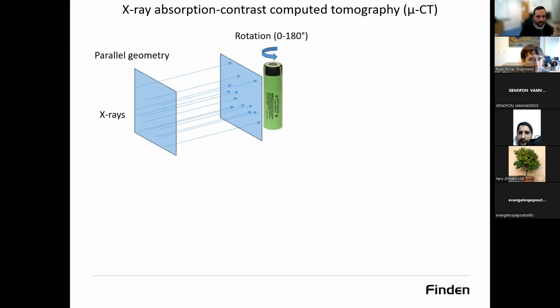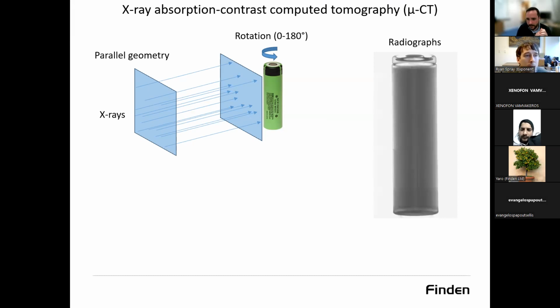But before we go there, let's take a step back and talk a little bit about absorption contrast tomography. You are probably familiar with these techniques through hospitals, so medical X-ray CT. It's essentially the same technique that we use to study materials and devices. In the simplest implementation, you have here a parallel beam geometry, it doesn't matter what it is, but we illuminate with an X-ray beam our object, for example, the 18650 battery here, and we're measuring the intensity of the transmitted X-rays through the sample. So essentially, we're collecting radiographs.